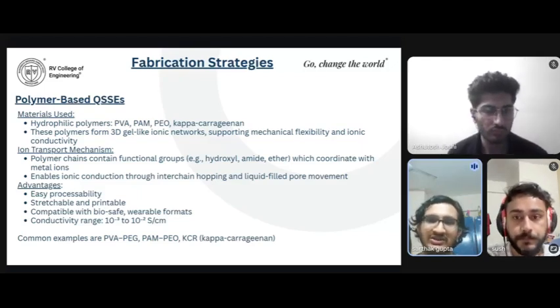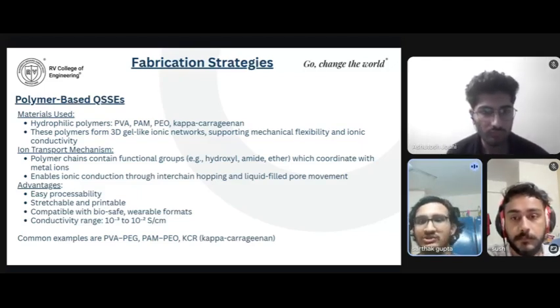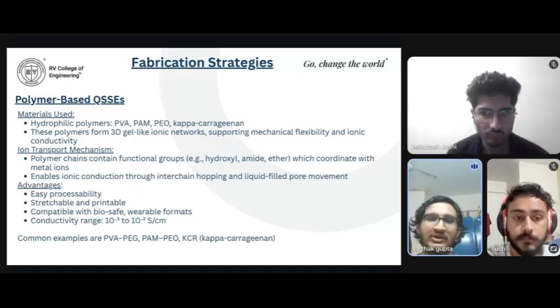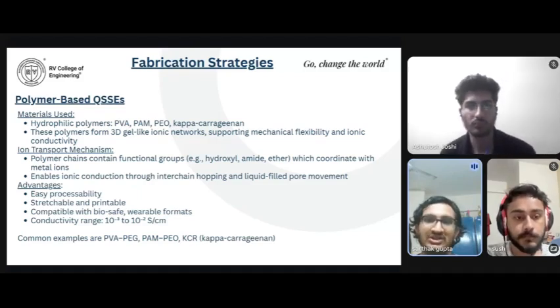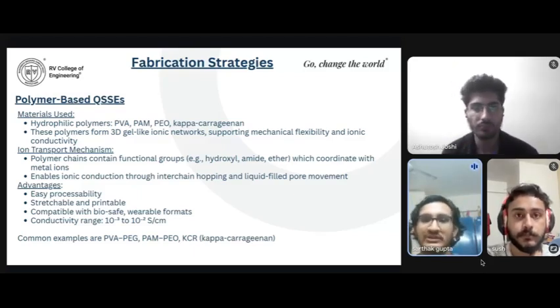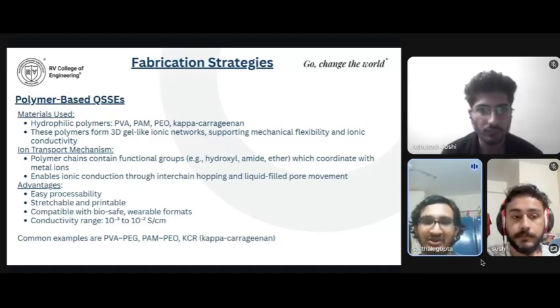These polymers are selected because they contain functional groups like hydroxyl and amide groups, which coordinate with the metal ions, as we mentioned in the starting, Zn2+ ions in zinc-ion batteries. These coordinate very well with the metal ions, which enhances the ionic conduction. The synthesis typically involves dissolving the polymer and salt in water or solvent, and casting it into a film or a gel-like structure, which is a quasi-solid state,